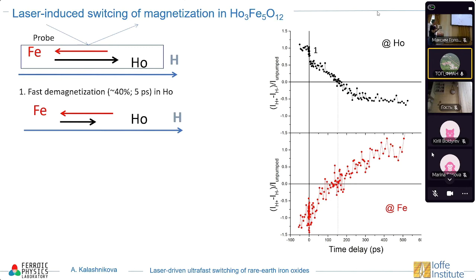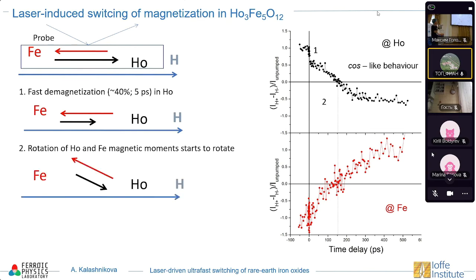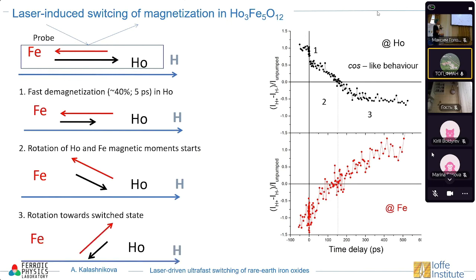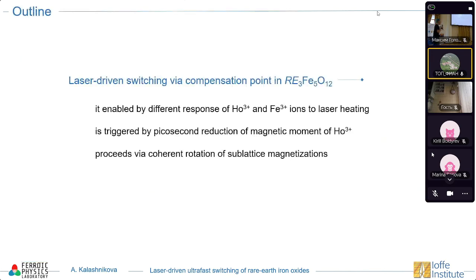So what happens then to the magnetizations, how do they start to move? If we look more carefully at this kind of dynamics, we see a half-cosine-like function. It means that iron and holmium, when they are in such a situation, just start to coherently rotate in order to align with the field. And it's a slow process, of the order of several hundreds of picoseconds, and it's complete over here. So here, by doing pump-probe spectroscopy in the X-ray range, we were able to demonstrate that there is indeed a different response of the magnetic moments of holmium and of iron to ultrafast excitation.